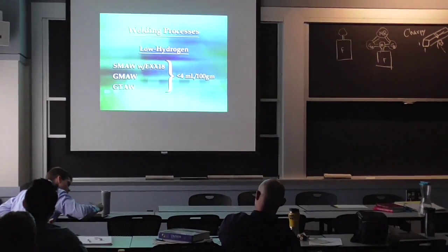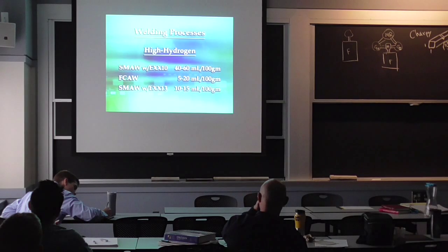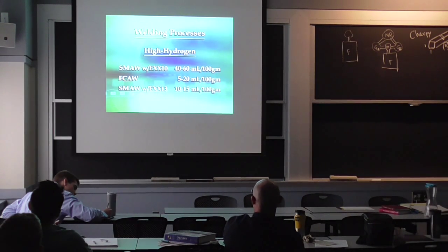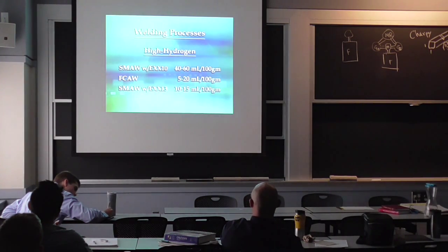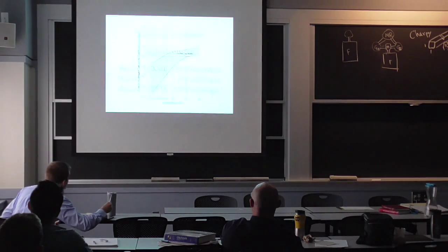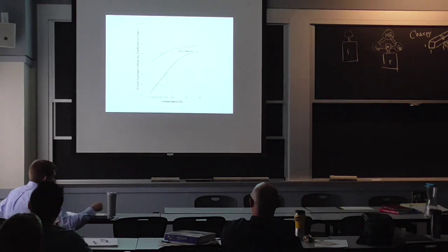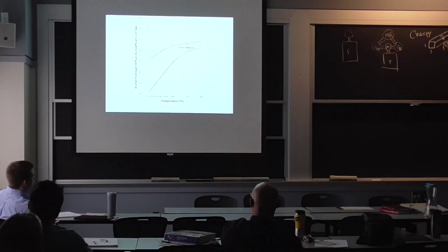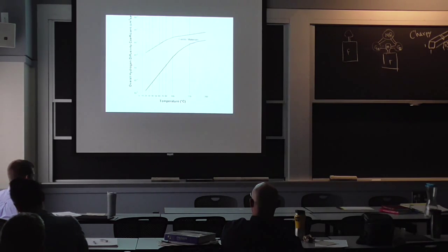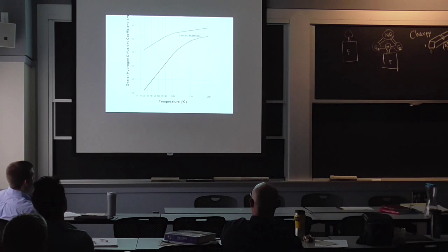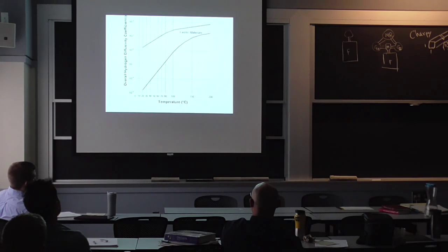In contrast, shielded metal arc welding with EXX10 type electrodes results in welds with hydrogen levels of 40 to 60 milliliters per 100 grams. That's 10 times more hydrogen. If a weld remains at high temperature after welding due to preheat, interpass temperature control, or post-heating, the hydrogen that was introduced into the weld has the ability to diffuse away.